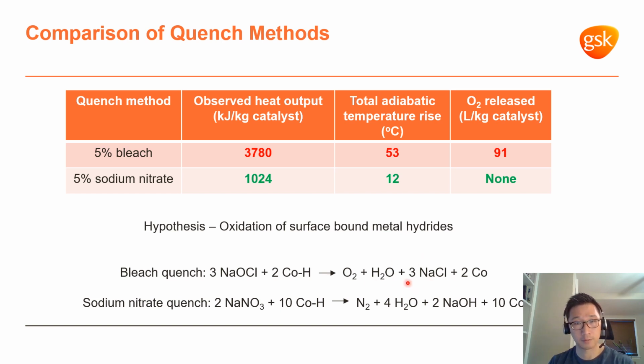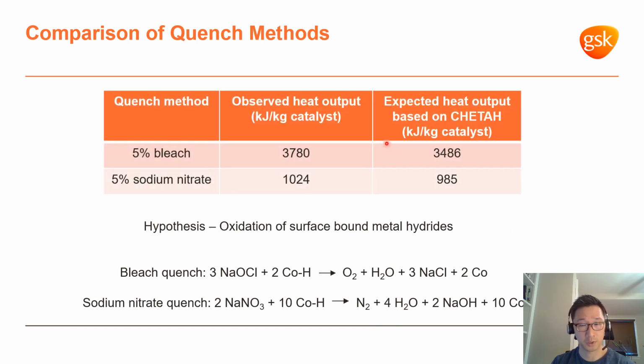Now, this is a hypothesis of ours, so in order to test it, our process safety engineers perform what's called a CHETAH calculation. And so CHETAH is just a standard process safety calculation where they can estimate the heat output based on published data. And so when we do the calculation based on these proposed balanced chemical equations, the expected heat output for each quench is very close to the observed value.